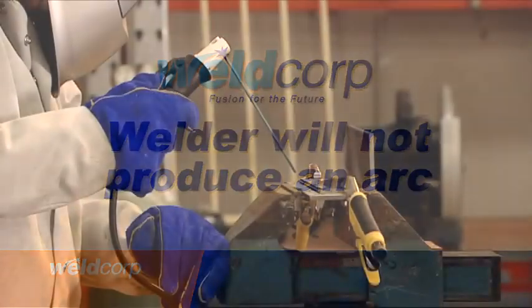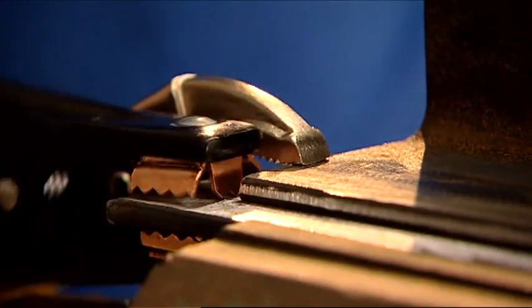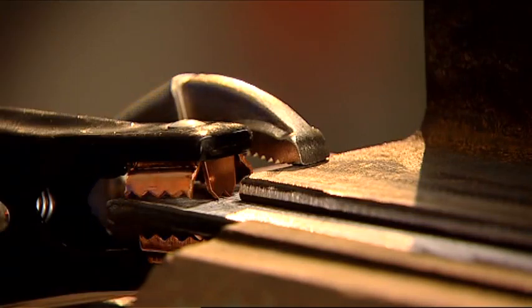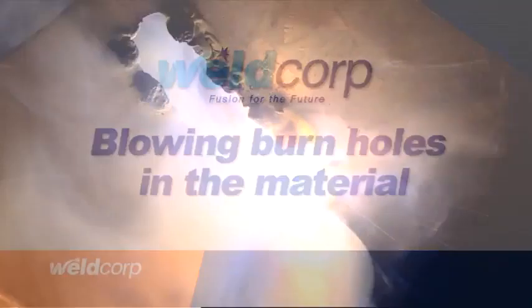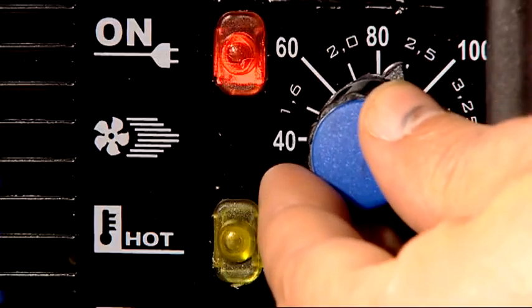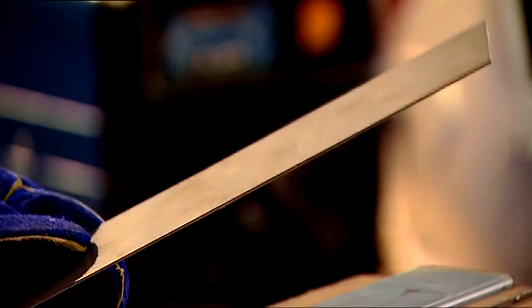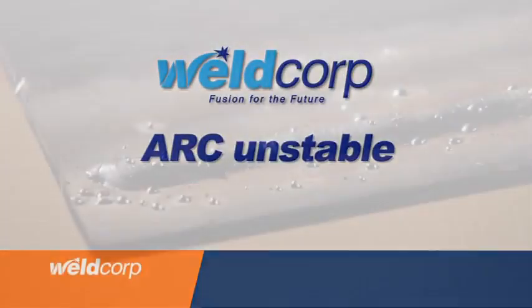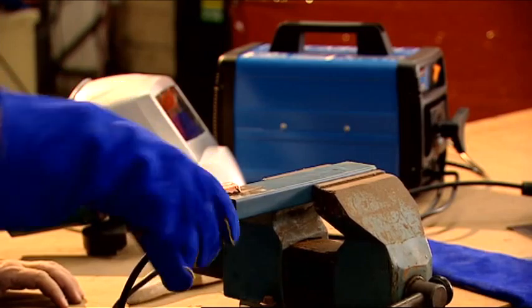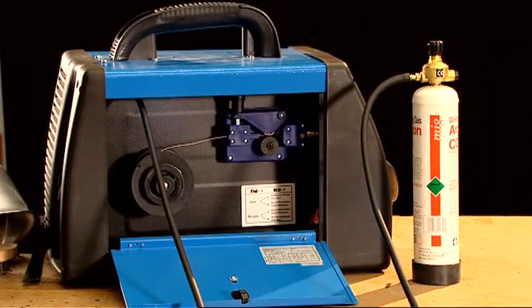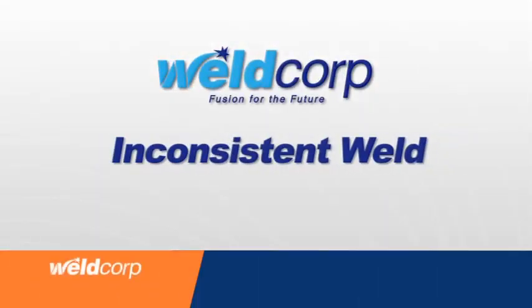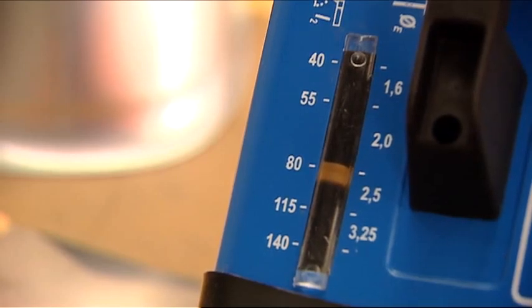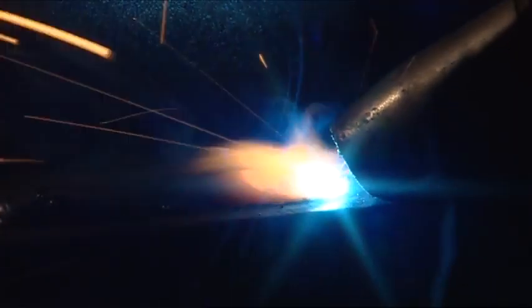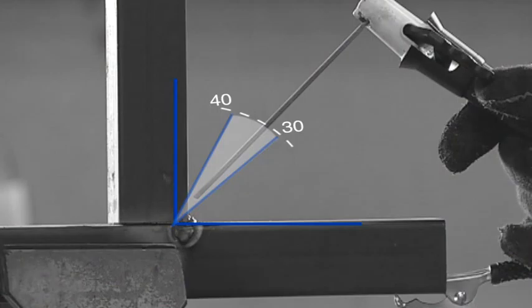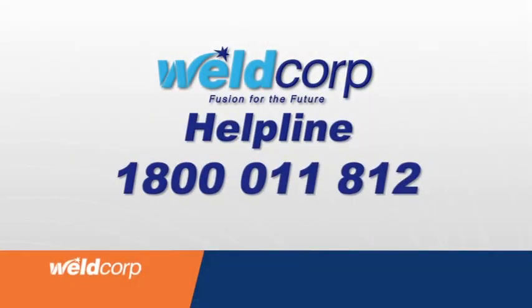Welder will not produce an arc. Check power connections and ensure the earth clamp is attached and has good contact. Blowing burn holes in the material. The amp setting too high or the metal too thin. Arc unstable. Dirty workpiece or poor earth connection. Damaged electrode or insufficient gas. An inconsistent weld. Check the amp setting. Check wire feed speed. Check welding angle and speed. If your problem is continuing, you can call the WeldCorp helpline on 1800 011 812.